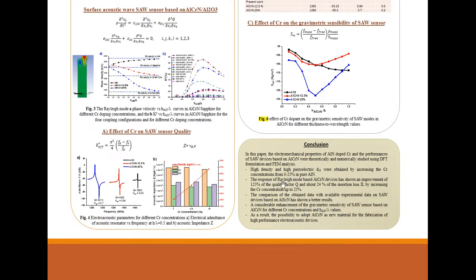The response of Rayleigh mode based surface acoustic wave device has shown an improvement of 125 in the quality factor and about 24 of the insertion loss by increasing the chrome concentration up to 25. The comparison of the obtained data with available experimental data on SAW devices has shown better results.